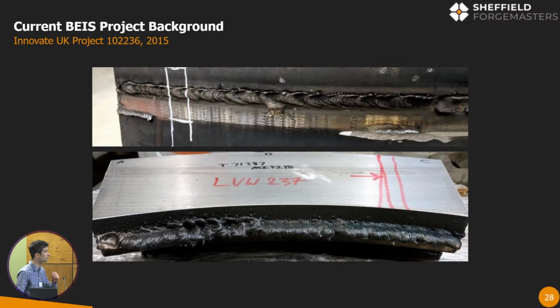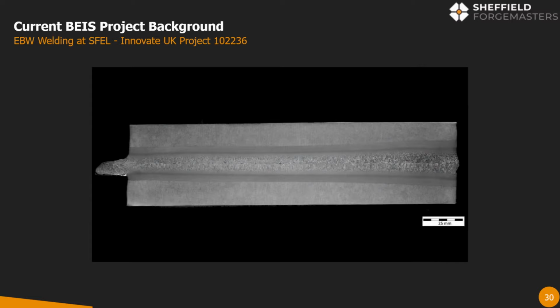Okay, so we're looking at an electron beam weld, single pass in a test piece. They never look that pretty, but when you take an X-ray shot straight through that, ignoring the end effects where the beam drops out of the sample, we showed that we could get dense, defect-free welds. It's very high intensity welding, so low heat put into the parent material, and very small, tight fusion zones.